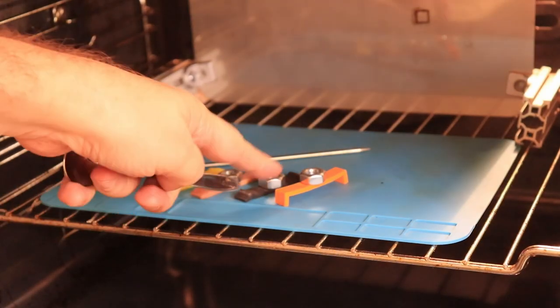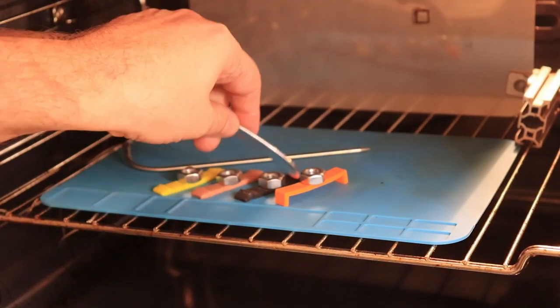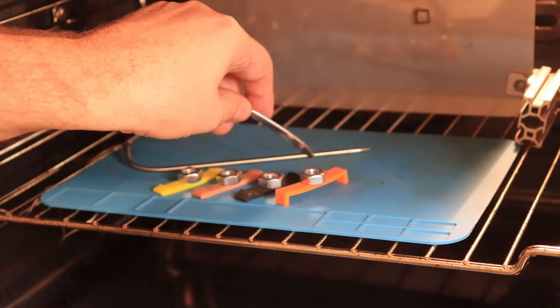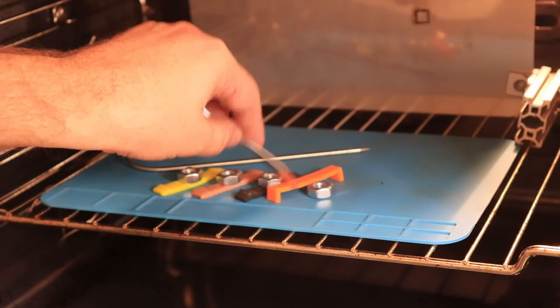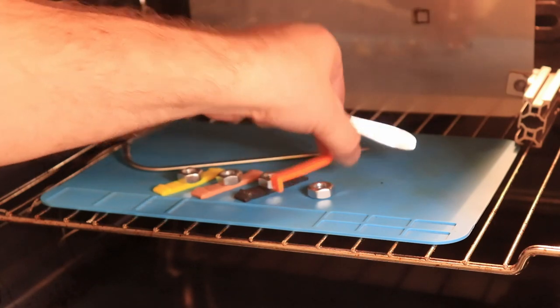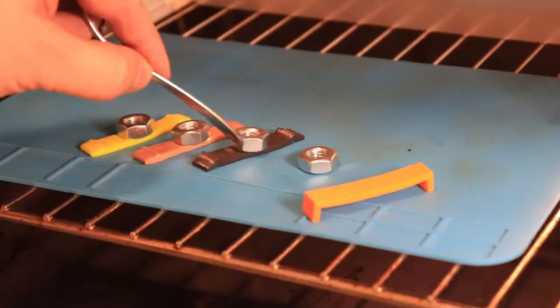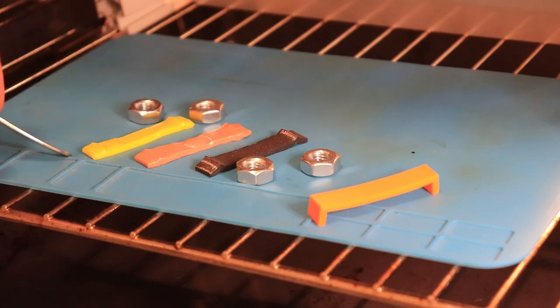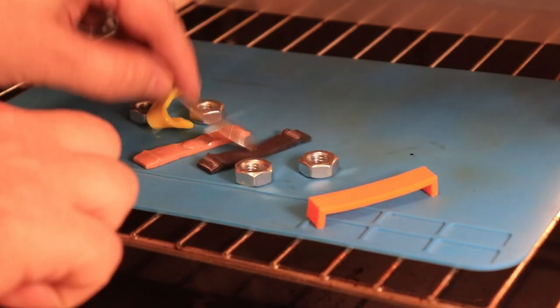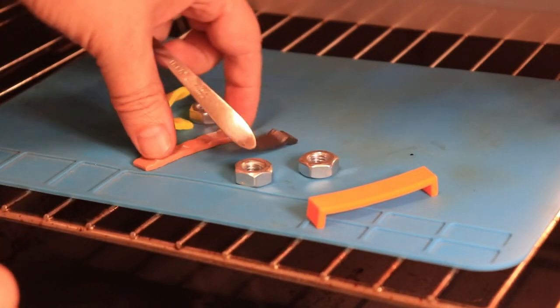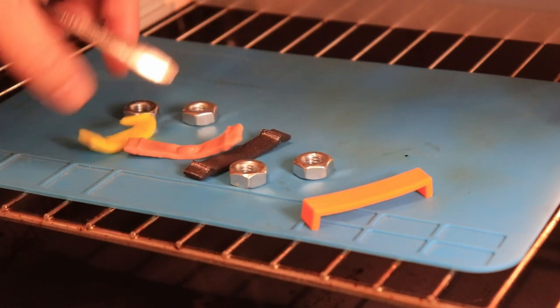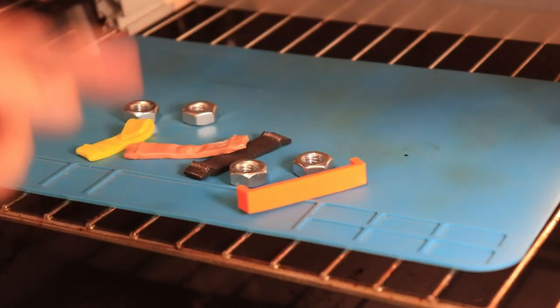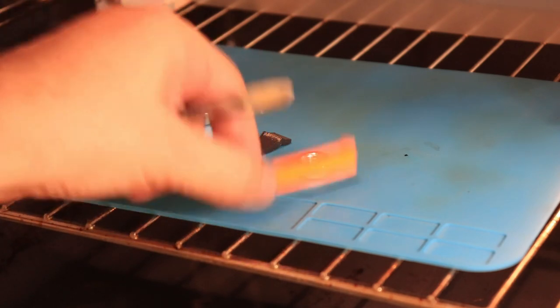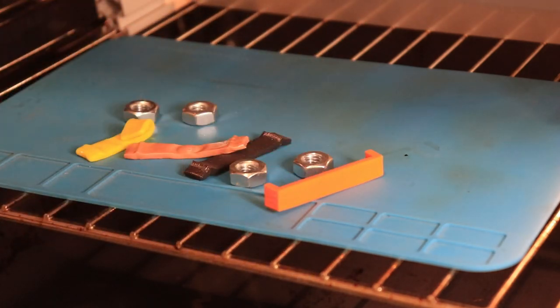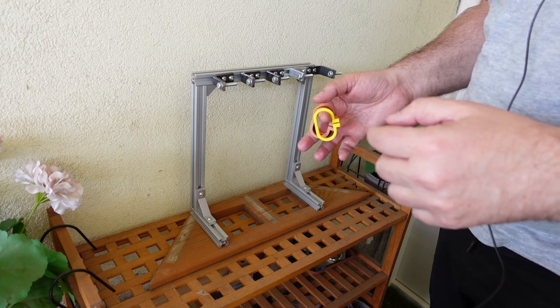And very impressive. I can see some deformation on the PC blend, but it still holds this nut, and it's quite hard. So if you need a temperature resistant filament, definitely PC blend is the best of these four. And it's time for the creep test.